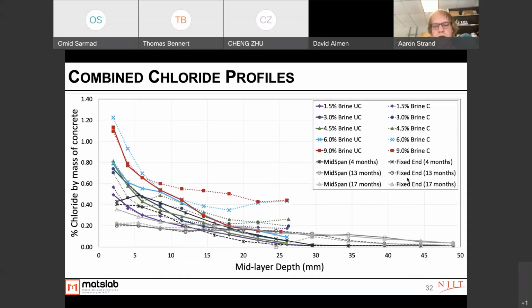Again, this is a combination of all the data, where we can see the comparison between laboratory specimens and the field specimen. The laboratory specimens, especially the cracked ones, do show a fairly high amount of chloride within them compared to the real specimen. So this is likely again due to the fact that we induced a crack versus what was naturally occurring from the actual finishing process and curing process of the deck.